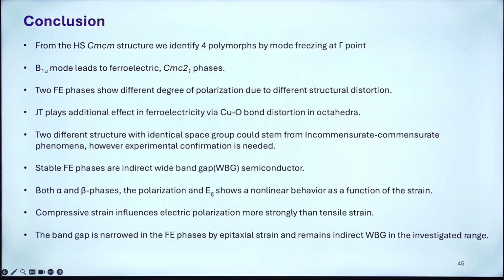And then the stable ferroelectric phases are indirect wide bandgap semiconductors. In both alpha and beta phase, the polarization and Eg show a nonlinear behavior as a function of strain. This is purely the effect of strain. Compressive strain influences electric polarization more strongly than tensile strain, and the band gap is narrowed in the ferroelectric phases by epitaxial strain, but the compound still remains semiconducting. There is a slight lowering in the band gap, but if it became metallic then it would not be a ferroelectric either.